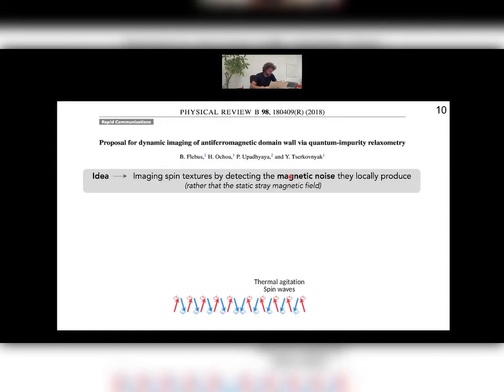So the idea is pretty simple. You consider an antiferromagnetic material. Here there is thermal agitation, or let's say spin waves or magnons, and then you will bring your NV spin above the sample to measure the magnetic field noise. And the idea here, and this is what is proposed in this paper, is that at the location of a domain wall, for example, there is an excess noise because there are additional magnon modes that can be populated, and at this particular location, you expect to detect an enhanced magnetic noise with your quantum sensor.